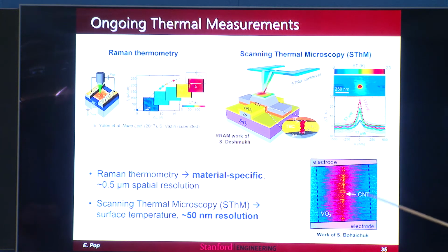In this case, she's using a carbon nanotube to trigger a nanoscale insulator metal transition in vanadium oxide, partly for physical curiosity and partly because it turns out there's some interesting applications, such as very small memory selectors that could be enabled by this. Maybe not with VO2, but with niobium oxide, but still this is a way to scale them down. She's also made oscillators out of this because it turns out the metal insulator transition is very unstable. So you can actually go back and forth if you bias the device in the right place.